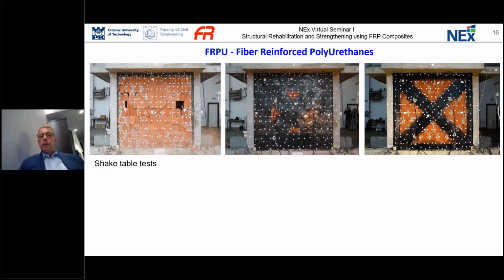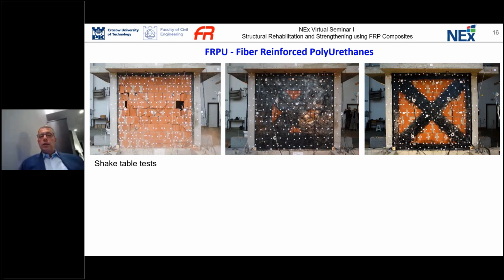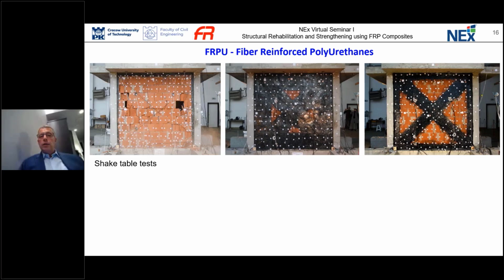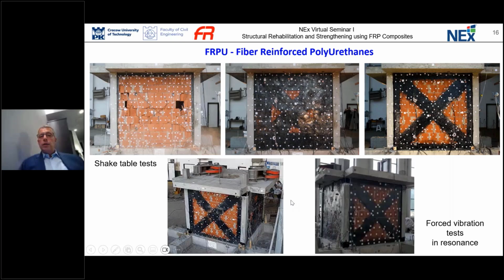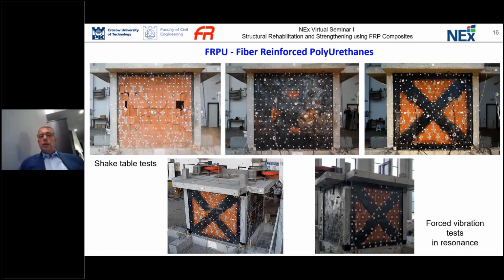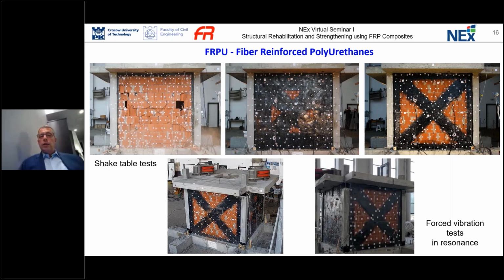After that, we protected this kind of infill walls with FRPU system. So in the middle, you see protection against failure of this kind of wall without any special application, smoothing of the surface. We bonded directly the fibers using the polyurethanes, and in this case, we were able to stiffen the whole structure. The owner of the shaking table was unable with this system to damage this kind of structure, so they promised to damage it with forced vibration in resonance, mainly by application on the top of special exciters, and try to damage it also. As you can see, in resonance, the duration of this test was 2 hours, and they were unable to damage this structure.